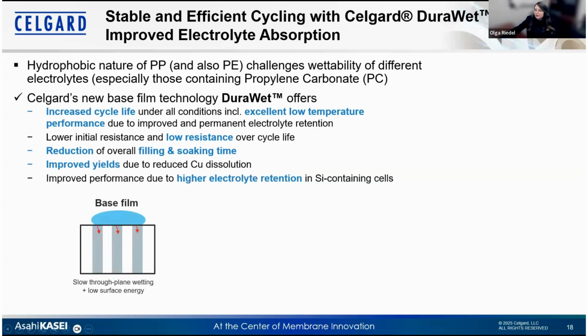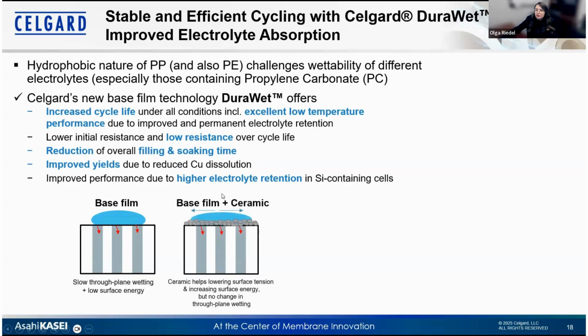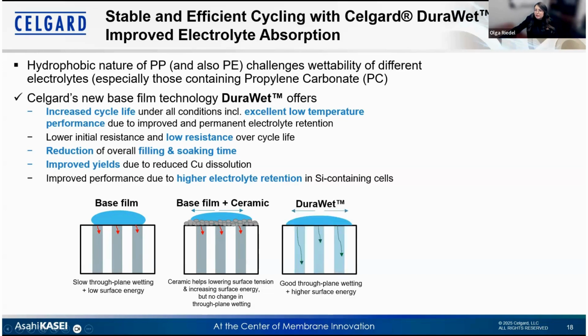In this schematic, I want to illustrate the poor retention of any type of polyolefin membrane with the electrolyte. While usually a lot of cell designers typically look for solutions such as ceramic coating, the ceramic coating only really helps to spread the electrolyte in plane, but it doesn't soak up the electrolyte into the pore structure. Our new DuraWet technology provides electrolyte retention due to higher affinity to the electrolyte down to the deepest of the pore structure.